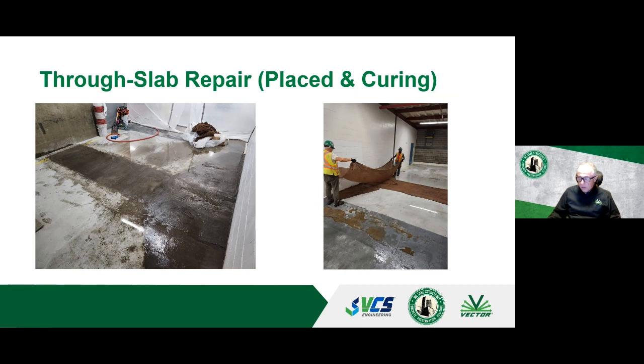The repair mortar used was a low moisture, rapid setting form-in-place material. And again, we were under the gun here to get it done. This material could be waterproofed within as little as 24 hours. And again, we had really good conditions here, a nice temperature. This was done in July, so we had to put extra guys on this to mix it and place it to ensure it wouldn't kick off in the bucket.